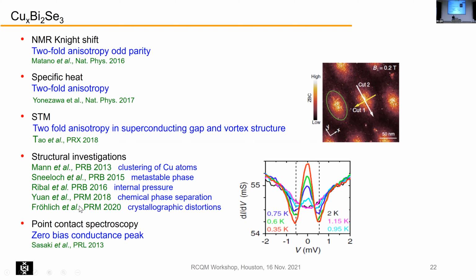This material has been very much investigated as regards its structural properties, and you can have all types of problems with these samples. But if you prepare them by electrochemical intercalation, as was done by Ando, you get really good samples with about 60% superconducting volume fraction. Speaking about zero bias conductance peaks, that was done by Sasaki, and they claim that they have some peak in the gap, and they claim it's a Majorana fermion state, but nobody will believe that, I think.